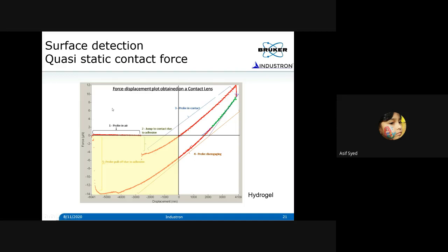At some point, you may contact, and normally you will jump to contact, okay? Because of the adhesion and because of the surface energy, the probe will be pulled into the surface, or sometimes even the surface is so soft, it can bulge and make contact with the tip. Any of those things can happen, okay? So when that happens, you make the contact between the probe and the sample, and then the force increases. Then you start to see the repulsive interaction. Before that, all that you are seeing is basically attractive interaction.